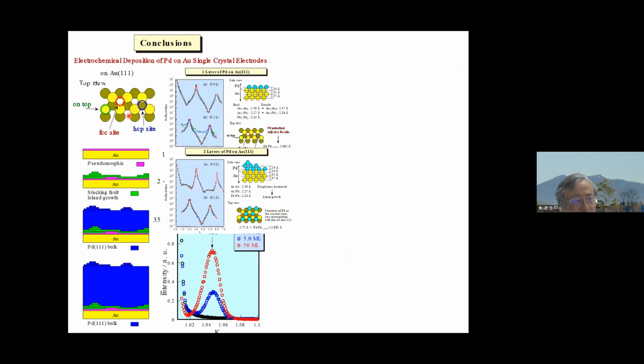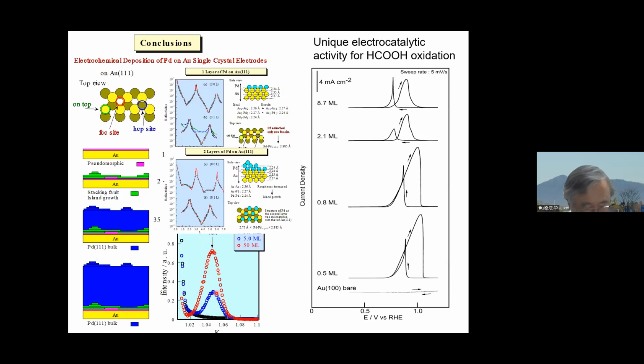So we did a lot, but to make the story short, we found that the first palladium deposits on the FCC site of gold, which means the palladium distance is the gold distance, not the palladium distance. But by depositing 5 layers, it already starts to show the palladium diffraction peak. When it is only 2 or 3 layers, we don't see the palladium peak. So the first few layers of palladium deposit on top of the gold, and then convert to bulk palladium. But these first few layers have very unique catalytic activities because of the different geometric and electronic structure.